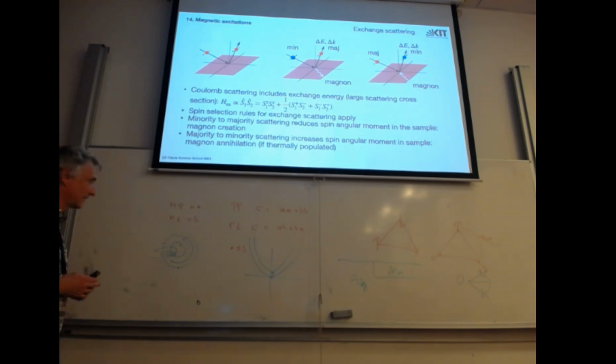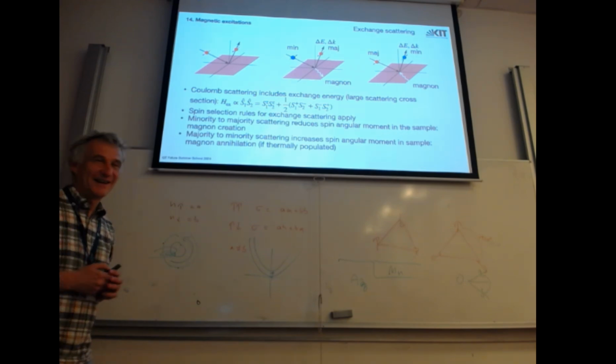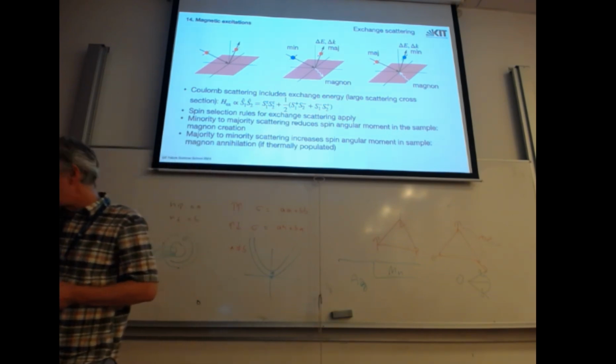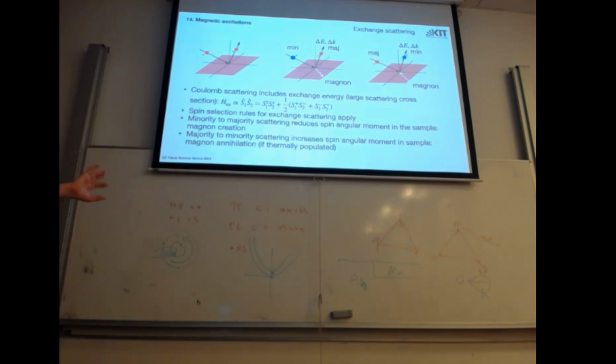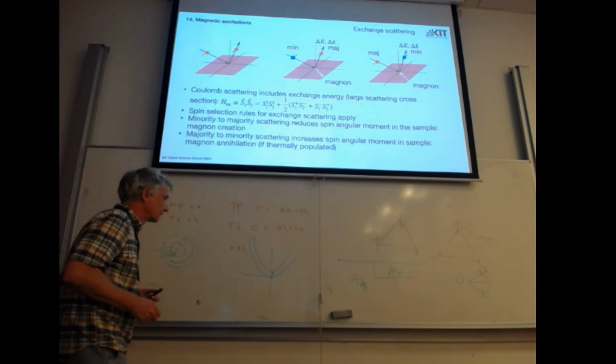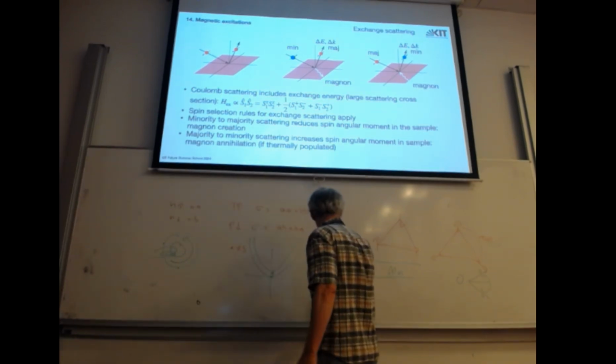Is it clear? I'm getting fast here now. Just like before in the phonons. In the phonons, we had the idea that our molecule can be in the barrier and there's no Q. Your argument is correct. But if I have the phonon inside the metal, then of course, for the electron before scattering, the K vector should be the sum of the K vector after scattering plus the phonon. Yeah, but then basically what I'm saying is that when you do the tunneling experiment, your momentum conservation is completely broken by the tip itself. No. This is not correct.